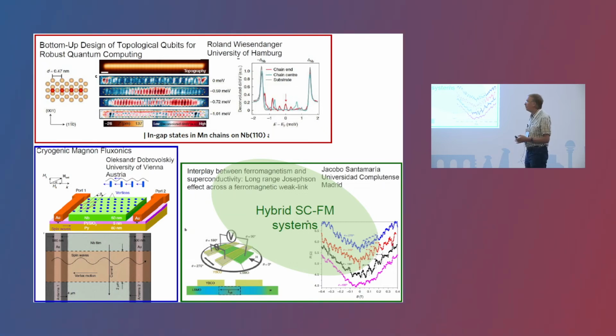It turns out that due to the hybridization of the electronic states of the superconductor with the electronic states of the magnet, under certain conditions a special modulation of the electronic structure in the magnetic chain takes place, and more importantly, coherent states at the end of the chains are formed within the superconducting gap. The idea is to move these states close to the Fermi energy to realize these Majorana bound states.